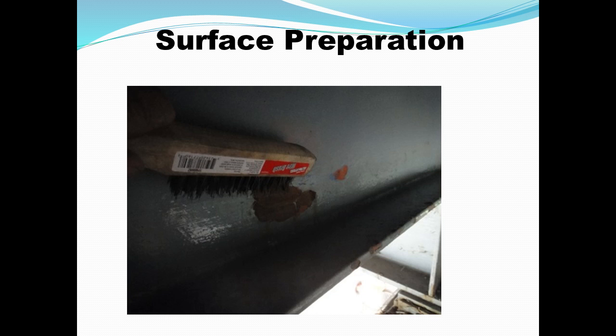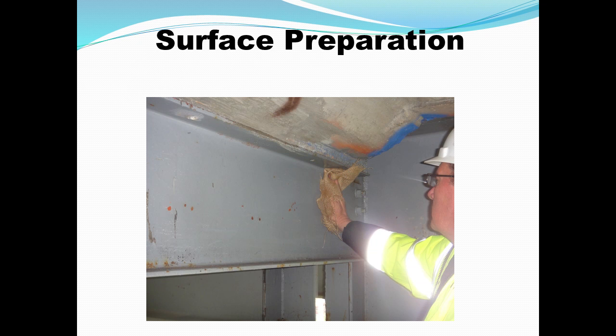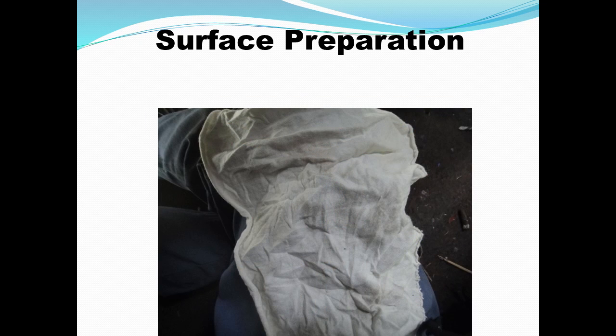to remove any of the loose material around those edges. That doesn't get it all, but it gets some of it. And then we wiped those areas down with burlap. I was surprised at how good a job burlap does for cleaning, but it can clean the surface up very well. And then each location was wiped with a white rag, and those rags were retained for future reference.